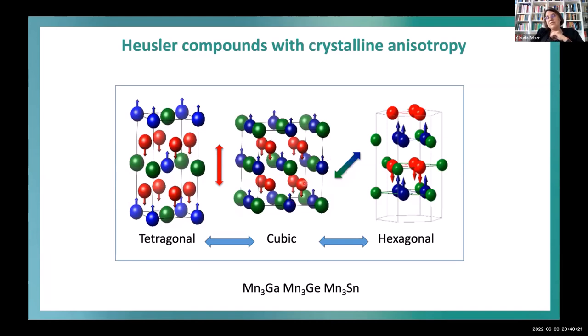So we already saw we have cubic Heuslers, which are quite soft, where we can have antiferromagnetic, ferromagnetic, and ferrimagnetism. But we could also strain them in the 1-0-0 direction, and we have a tetragonal Heusler compound. Or we could strain them along the 1-1-1 direction, then we end up with a hexagonal structure. And indeed, many of these Heusler compounds, if you look in the phase diagram at very high temperature, it's very complex. So you can more or less sometimes even design all three. For example, manganese gallium: people made hexagonal antiferromagnetic Heusler compounds, they made nearly compensated cubic ones and tetragonal ones. So very often, depending on the temperature and slight differences of composition, you can design all of this.